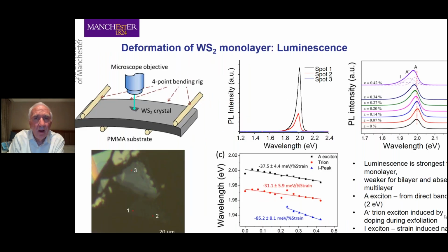Now, what I want to do is, again, related to the first talk, but doing something slightly different. And that's looking at these other 2D materials, tungsten disulfide or molybdenum disulfide, which show luminescence. And luminescence is very interesting compared to the Raman spectroscopy, because essentially you use the same hardware, the same instrument. So if you have, say, a tungsten disulfide crystal or molybdenum disulfide crystal on a substrate, you can get a luminescence spectrum. We also saw in the first talk that the luminescence is particularly strong for monolayer and then decreases in intensity as you go to bilayer and trilayer materials. So this spot 1 is monolayer, spot 2 is bilayer, spot 3 is essentially bulk material.